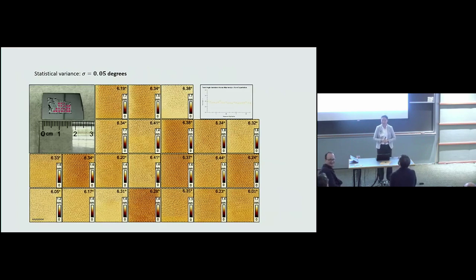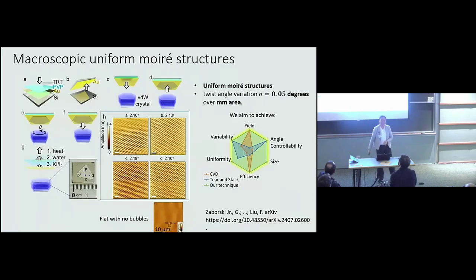Aren't you left with some contamination on the top layer because of... That's a really great comment. Yes, that's a really great comment. I'm glad you asked about that because I forgot to say it. So this is the AFM image of the surface. It's actually very clean. The root mean square roughness is 300 picometers.